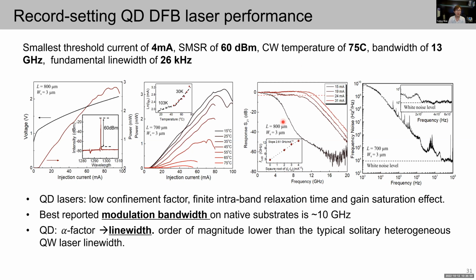But here, we got a record high value of 13 gigahertz with just polished facets, which means there still remains a lot of room to improve the modulation performance. For example, adding appropriate facet coatings, depositing metals on a thick dielectric for low capacitance, etc. So we can make the value even far more than 13 gigahertz.